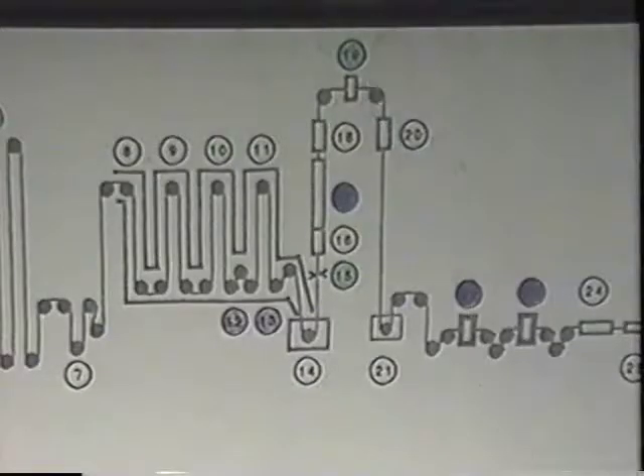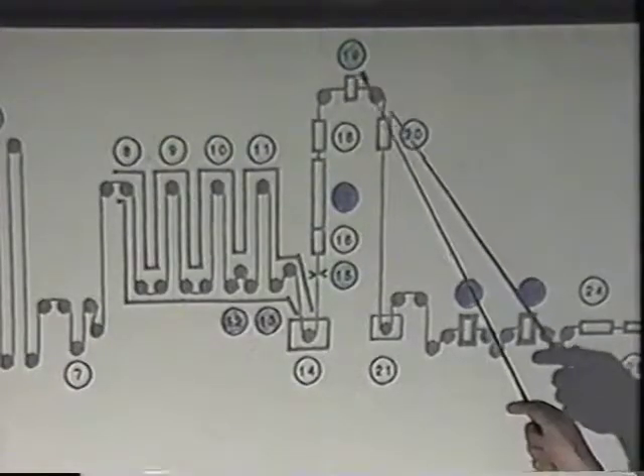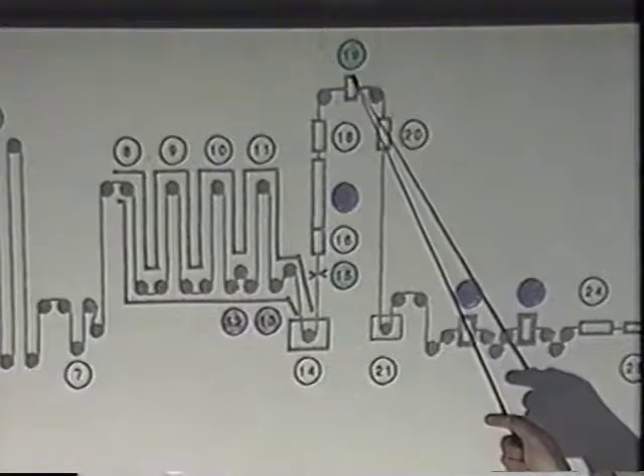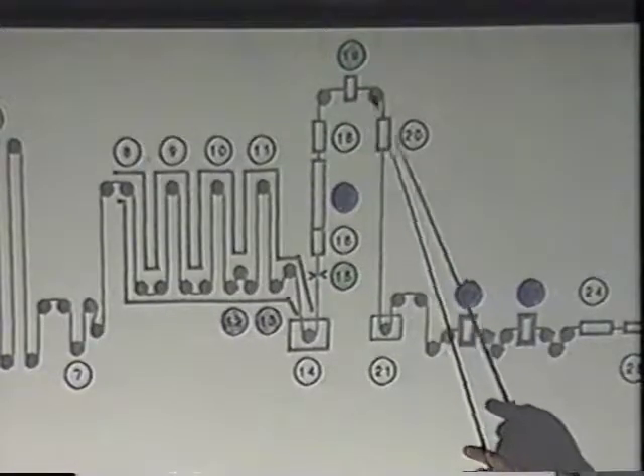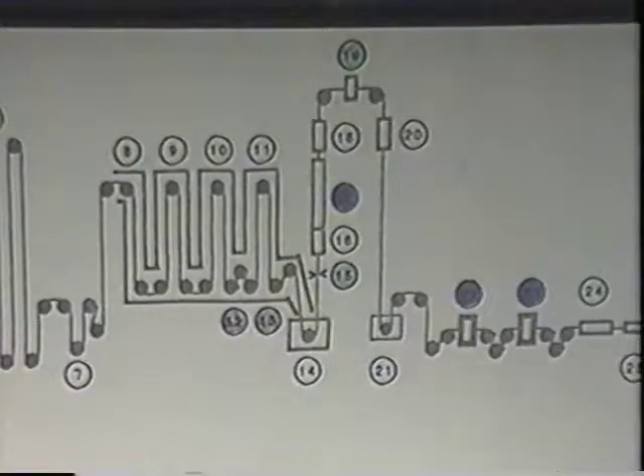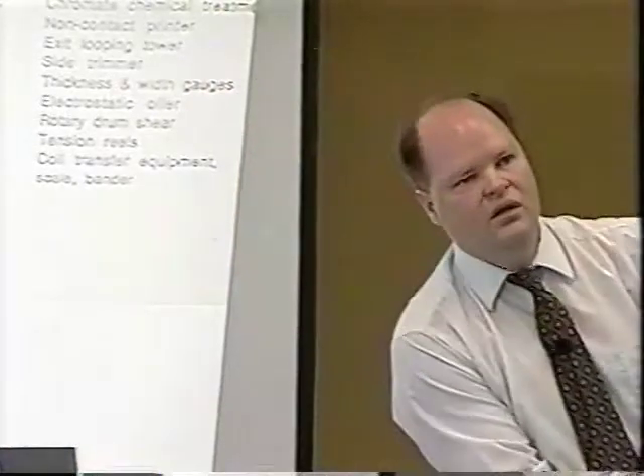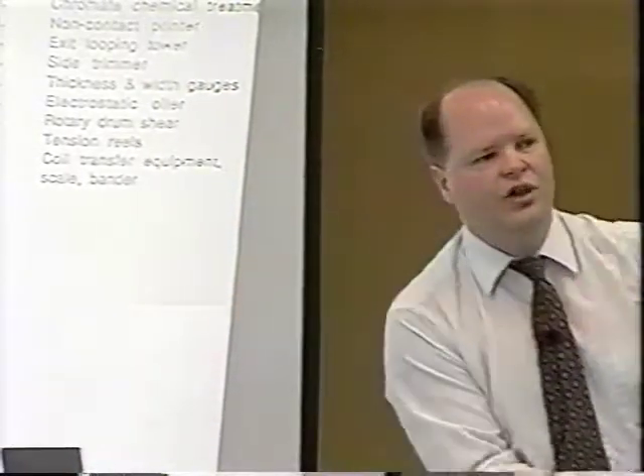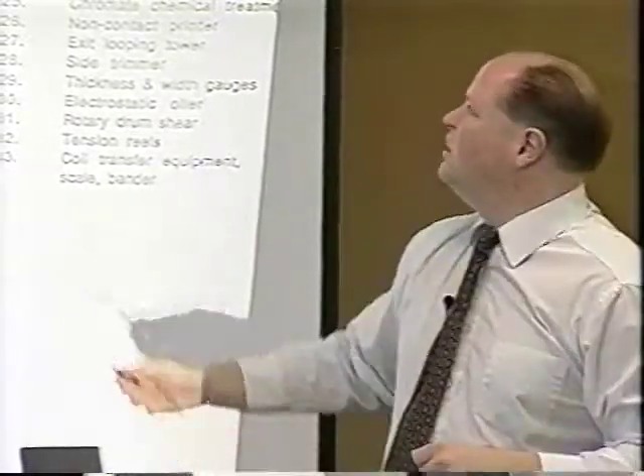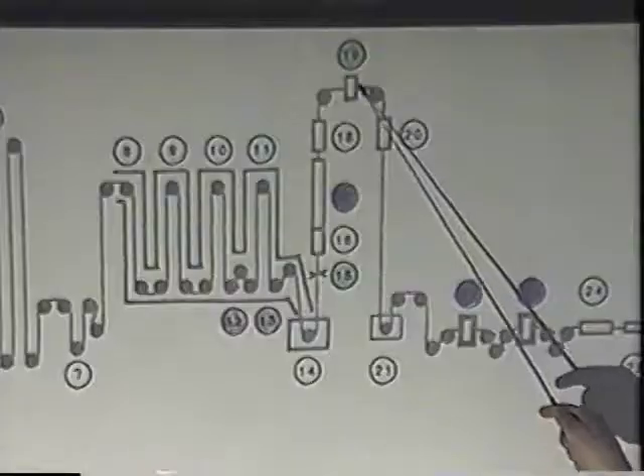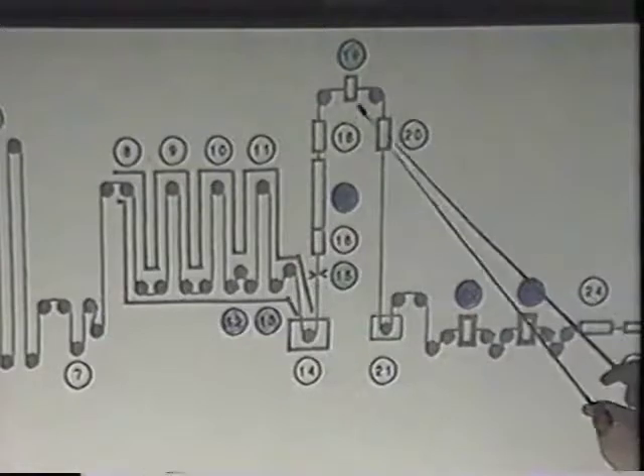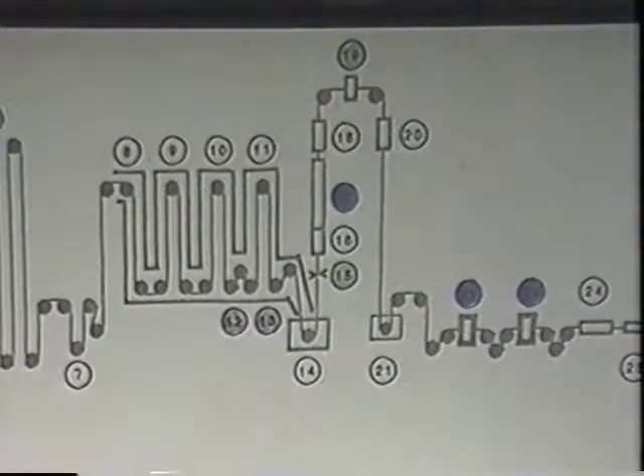So that's the X-ray gauge on top, and there's actually two X-ray gauges, one for the top of the strip and one for the bottom of the strip. And those gauges are scanning back and forth across the strip, measuring the coating weight across the width of the strip, and as the strip is running, of course, across the length of the strip. And those are tied in. The one on top will be tied into that air knife, the one on bottom will be tied into that one to control the coating weight.